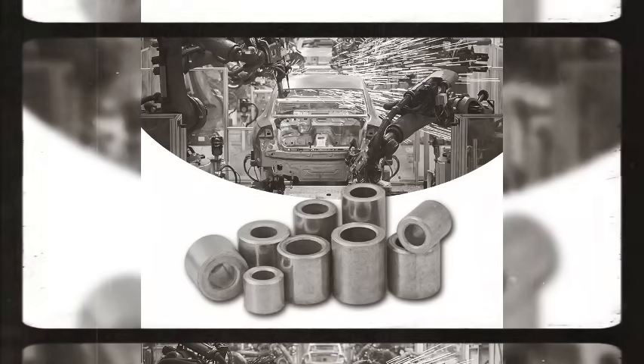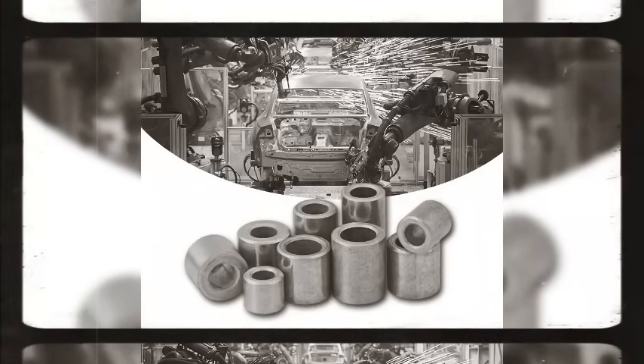Material variants have evolved beyond the original bronze. Super Oilite, an iron-based sintered bearing, harder and stronger than bronze, rated for higher loads but slower speeds. Oilite Plus, standard bronze impregnated with oil plus PTFE particles, reducing friction by approximately 17%. Aluminum Oilite, lightweight bearings for aerospace applications. But the original bronze-tin composition remains the most widely used, designated ASTM B438-95A Grade 1, Type 2, and SAE 841 in industry standards.